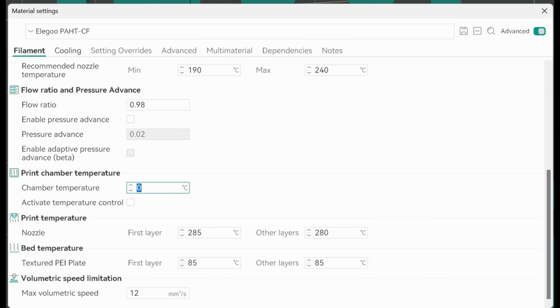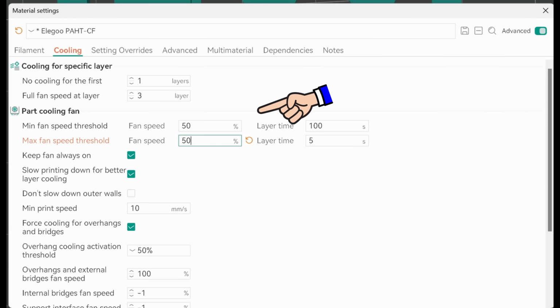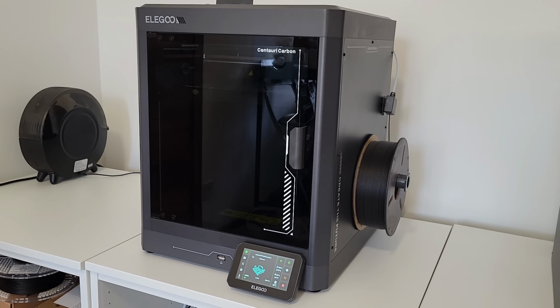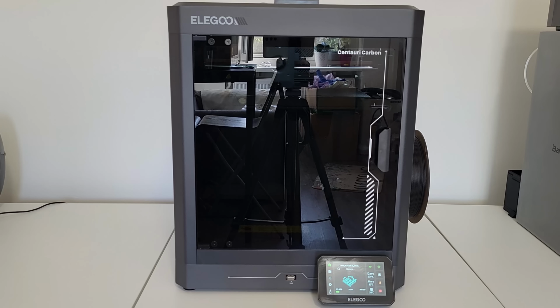Settings in the slicer: the nozzle at 280 degrees Celsius, 85 on the bed, 12 is the maximal flow rate, and 50% will be the maximal part cooling. Objects are printed on the Centauri Carbon behind closed doors. The printing was smooth without any problems, even if it is hard to see through this glass.